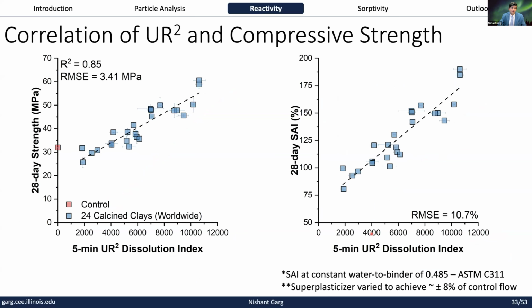Here also, if you look at the 28-day strength of mortars made with cement replaced with, let's say, 20% calcined clays, we again see a very decent correlation. And on the strength activity index test, we also see a correlation where you can predict that SAI value reasonably well. One very important thing to keep in mind is that we cast these systems at both a constant water to binder ratio as well as a constant flow. So we are taking the European approach as well as the American approach. We call it the mid-Atlantic standard, because if you don't do both of them, you can run into a lot of issues, since some of these materials with very high strengths can also have very high water demand. So you have to be very careful how you cast these mixes.